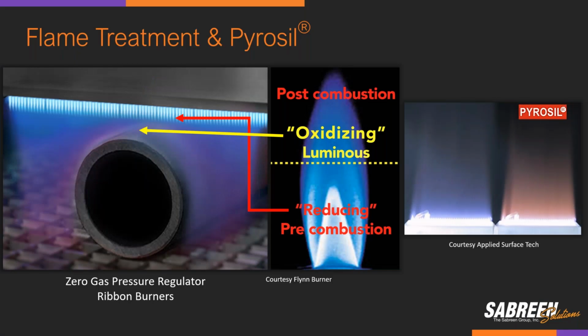Flame plasma treatment uses highly reactive species in the combustion of air and hydrocarbon. While flame treatment is exothermic, heat has actually nothing to do with the chemical functionality and the improved surface wetting. Flaming will clean dirt, debris, and hydrocarbons from the substrate.